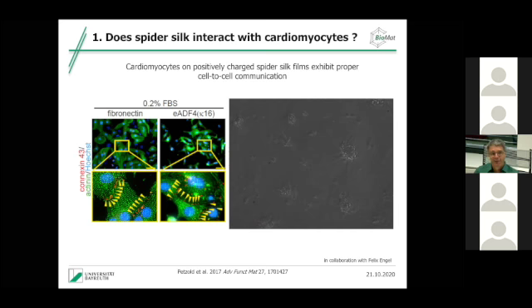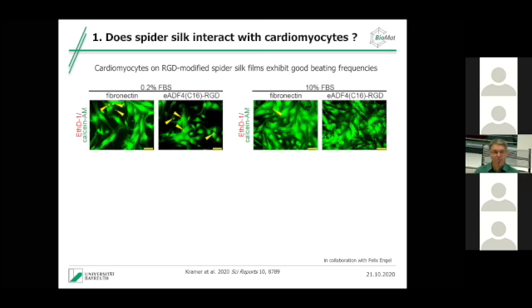The question is, can we also use other silk engineering? And as mentioned at the very beginning, we can introduce also cell binding motifs like the RGD. So we tested again now, this is our workhorse, the negatively charged protein, eADF4. You know what that means. E, this is glutamic acid, so they have a lot of negatively charged groups. And now we added the sequence RGD. And you see now all of a sudden, well, this surface is also good for cardiomyocyte adhesion. And even if we increase the concentration of the fetal bovine serum, you see much nicer proliferation.